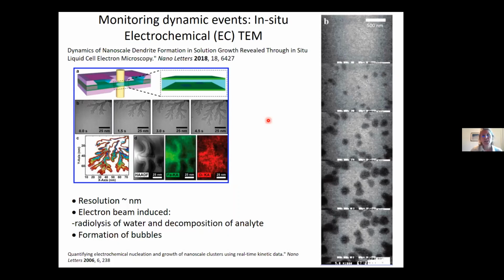So this is a powerful technique. In terms of resolution, I would say it's not quite there to get to your single atom. If you look at the in situ TEM images, you'll see that you can't see isolated single atoms. People are working very much in this area, but obviously we're putting this high intensity electron beam through an electrolyte. So we have to worry about what that process is doing itself. And in fact, people have used this process to actually induce growth of nanoparticles in solution. And then bubble formation and evaporation of the solution can be a real killer experimentally when you're doing this.